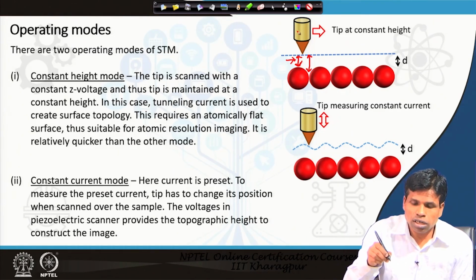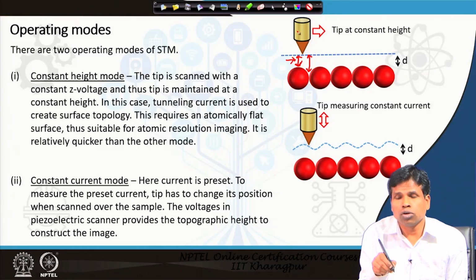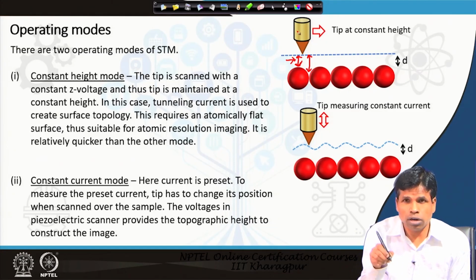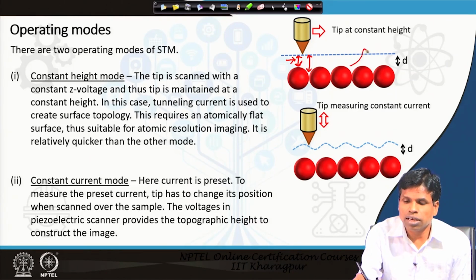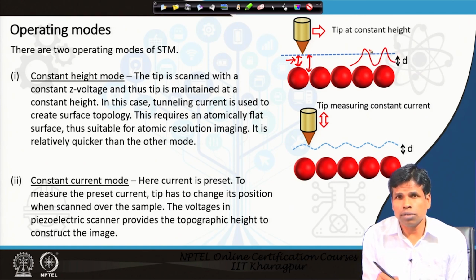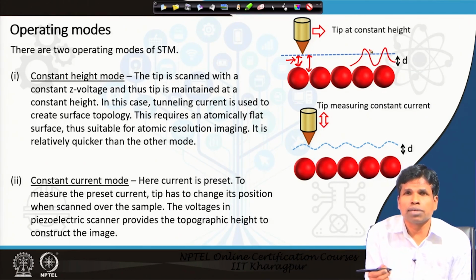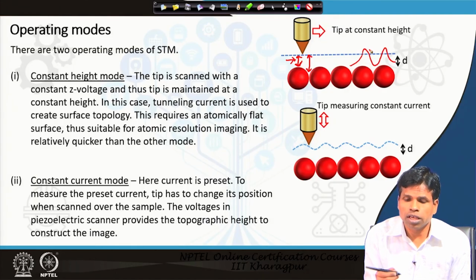So, the advantage is that we can do scanning very quickly, but it also has a disadvantage: if the sample is very rough, then the tip may crash. Once the tip crashes, artifacts will be generated, the tip shape will be distorted and artifacts will form. So, this type of study can be done for an atomically smooth sample. If we already know that the sample is very smooth, then we can use this mode.